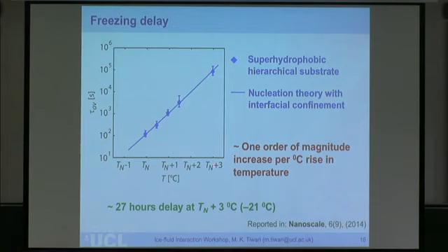But if you go just slightly higher, a few degrees higher compared to nucleation temperature, we are still at minus 20 degrees centigrade, and we can achieve very substantial freezing delay. So this is telling us, this is not hypothetical, this is experiment, by the way. So at least in these controlled conditions, we start to gain a sense of how we should go about designing surfaces and how precision is required. It's not just something that we want to do because we can. All right?